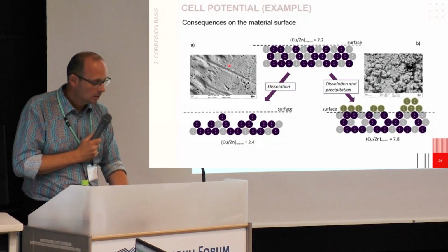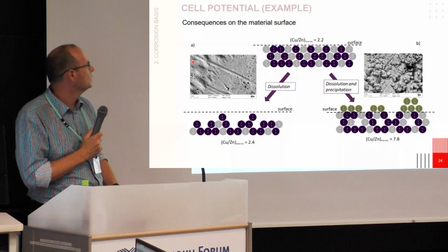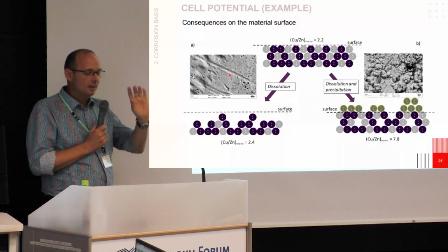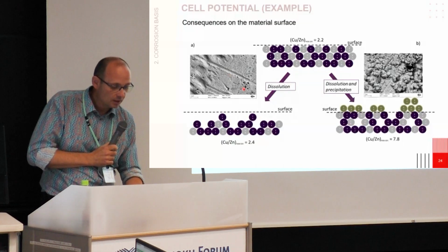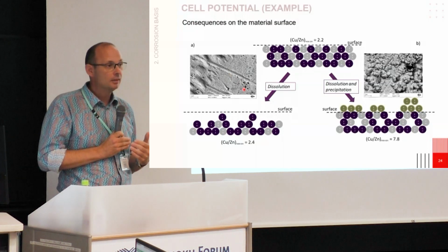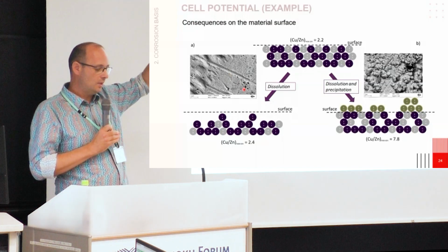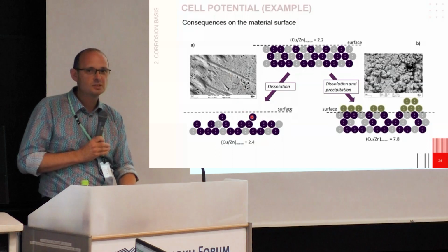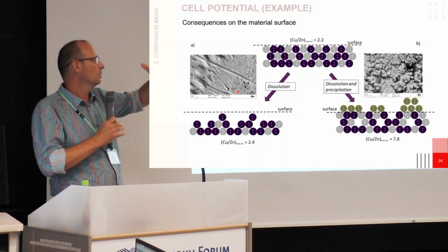So let's have a look. Here, this is the boundary of the cell. So that means here I have a small leakage, but let's focus here. That means that we should have holes in the metals which appear here. Actually, both elements are dissolving, zinc and copper, and they are not dissolving at the same kinetic. So all the surface is dissolving, which is summarized here, but the copper resists a little bit more than zinc. So that's why you have a very disturbed surface.